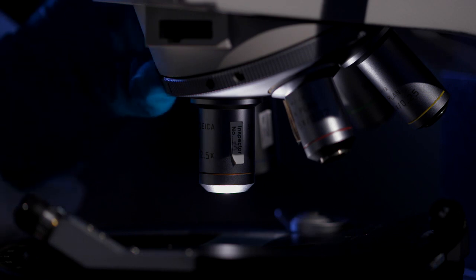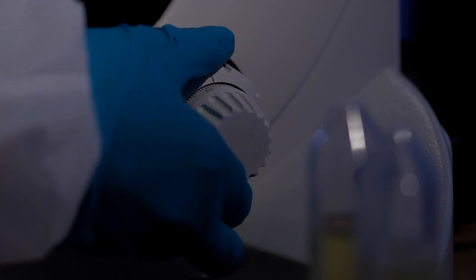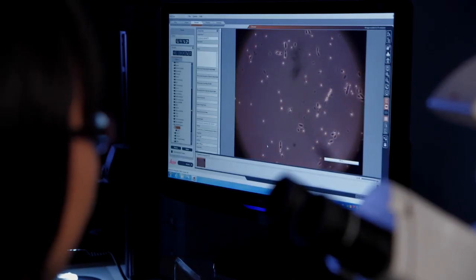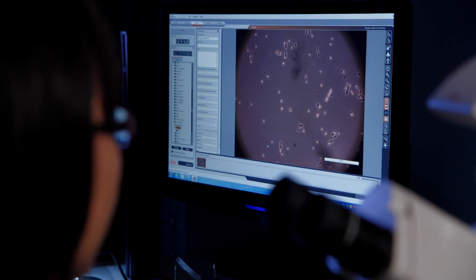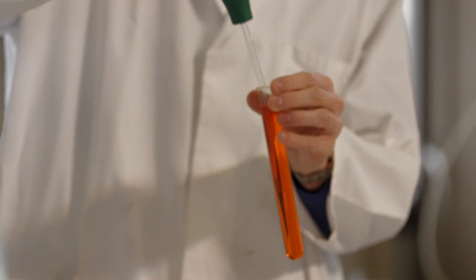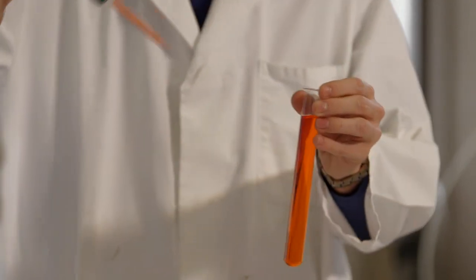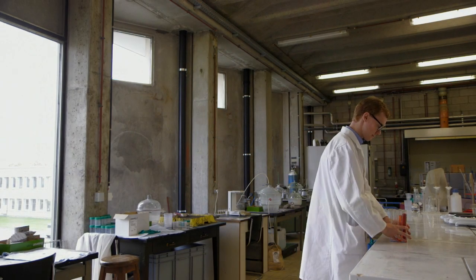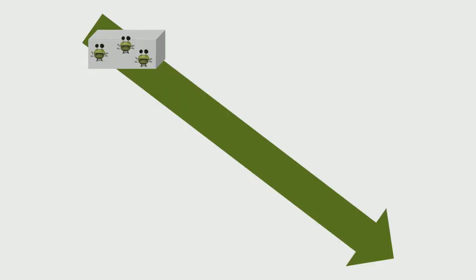As the bacteria need to survive in the concrete without nutrients until the moment that the crack appears, they are added to the concrete mix in a dormant state. These dormant bacteria become active as soon as they come into contact with nutrients and water, which intrude via the crack. However, these bacteria cannot directly be added to the concrete matrix, as they would be crushed in the small concrete pores during hardening. Dormant bacteria are embedded inside concrete.